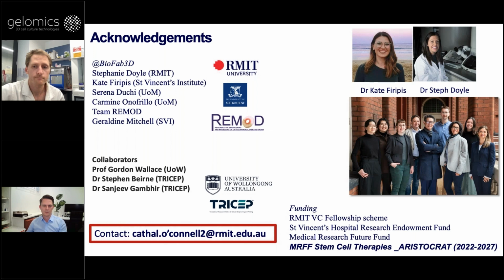Okay, no, fantastic. Also, you showed with filter sterilization that preferentially the larger molecules are being retained in the filter, which obviously makes sense, and the overall average molecular weight also decreases. So certainly something that users of GelMA should think about. I think there's also a lot of protocols out there that recommend dissolving GelMA at, let's say, 60 degrees. Of course, it is much quicker than 37 degrees, but it can also hydrolytically and thermally degrade the material and lead to unforeseen reduction in molecular weights there as well.